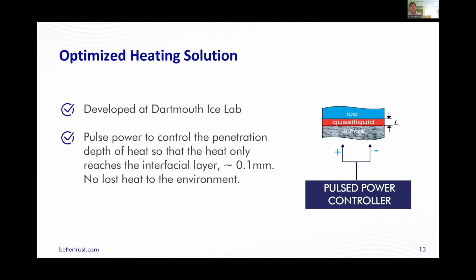And the idea for this comes actually out of the Dartmouth College of Engineering ICE lab. There they studied how ice forms, the way it adheres to surfaces, and the most efficient way to remove it from surfaces. And the key insight, from a physicist there who was really studying this at a first principles level, was allowing heat to reach only the interfacial layer of ice, shown in that red band on the right side, that quasi-liquid. So that the heat melts it, you get a thin layer of water, and then the ice can quickly be removed. And the best way to do that was pulsing energy in a way that keeps it right at the surface and doesn't go any further than, let's say, 1/10 of a millimeter where that interfacial layer is.